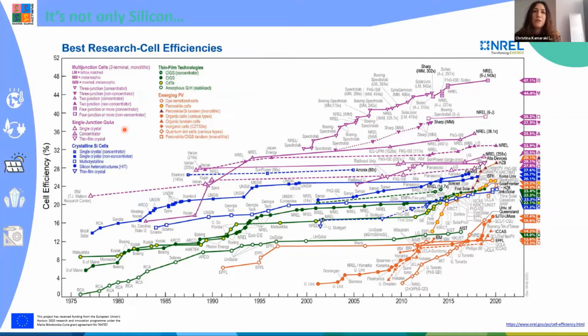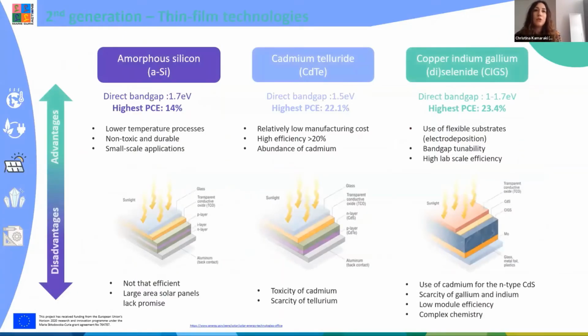So let's explore a little bit the other solar cell technologies. Moving on to the second generation of solar cells, we have the thin film technologies. The main feature of this family of solar cells is that we have absorbers with direct bandgap, and thus we can have thinner absorber layers, up to 10 micrometers. So imagine one order of magnitude lower than crystalline silicon. In this family, we have first amorphous silicon, which has a bandgap of 1.7 eV, but unfortunately, its efficiency is quite low. It's around 14%. So this is quite limiting for large area applications.